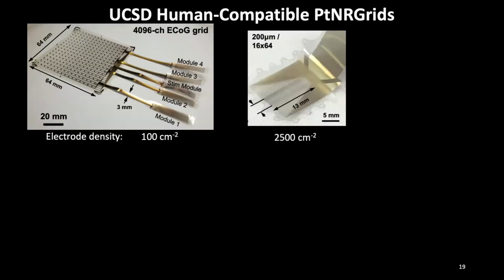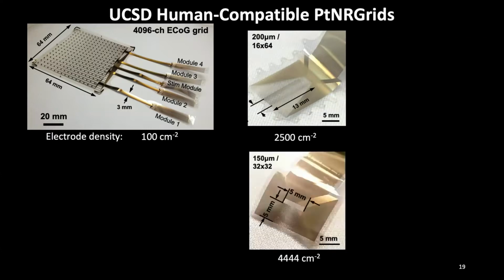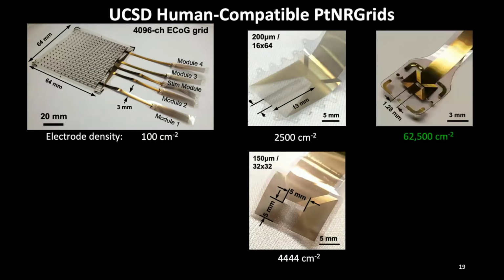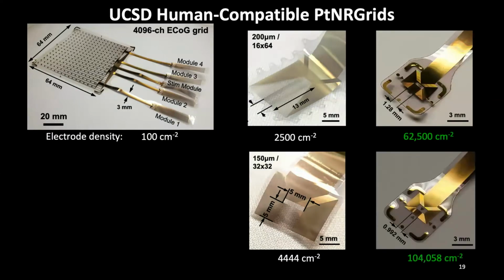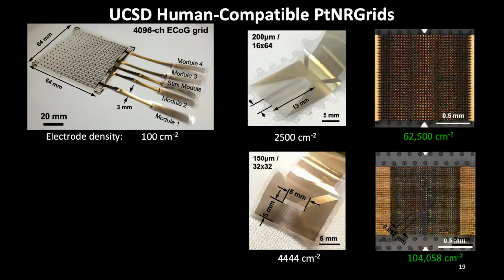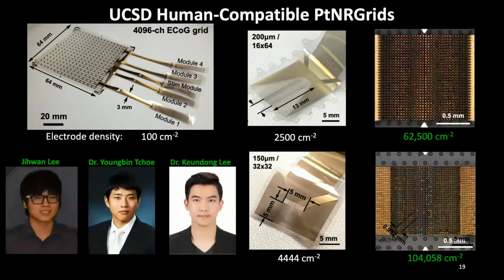The design is tailorable, so you can change the distribution of the contacts based on the area in the brain that you want to record from. So these are different versions in the middle, the 200 micron pitch is for recording from the superior temporal gyrus in language tasks, as I will show a little bit later. And then we have high density rat electrodes showing in the other three figures with the density of up to 100,000 per centimeter squared.